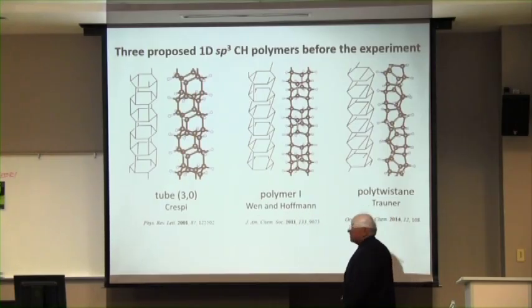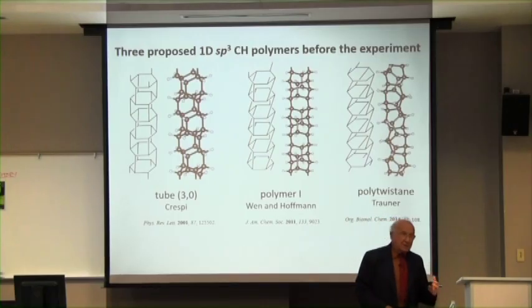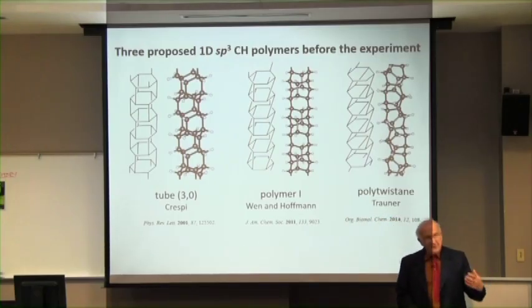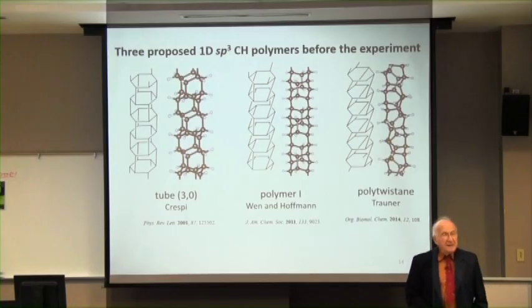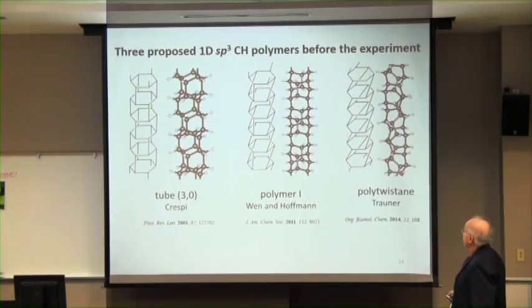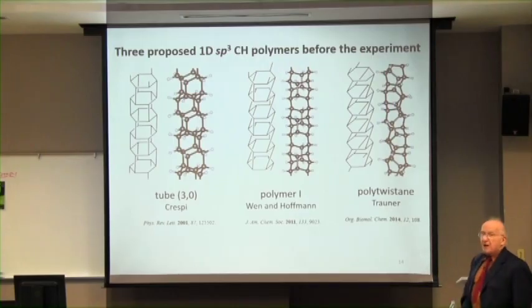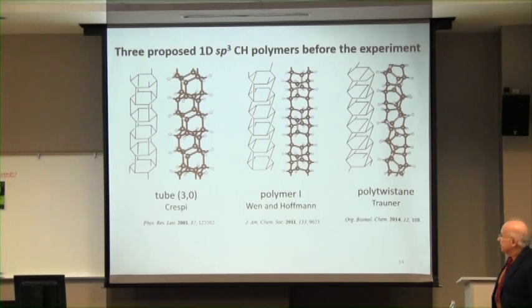We had a paper on a compression of benzene, on what happens to benzene under pressure. And in that paper, by chance, we found a polymer, a one-dimensional polymer at a much higher pressure that we predicted might come out from compressing benzene. This is a little more difficult to see, but you can see here a benzene ring, then another benzene ring, and another one. And there are sometimes linkages of 2, sometimes of 4. You can see this in various ways. We called it polymer 1.